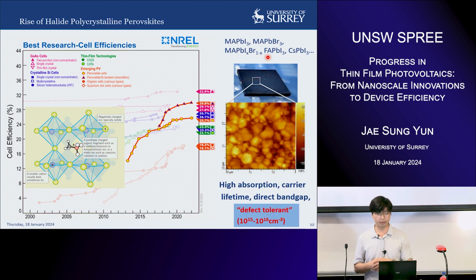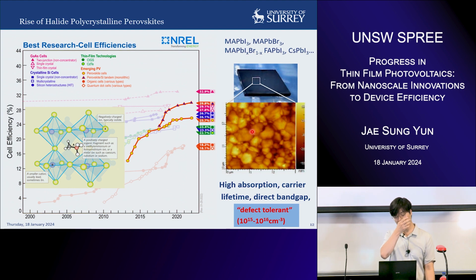A good thing about halide perovskite is that it is known to be defect tolerant. When I first saw this material, you could see that there are obviously a lot of grain boundaries. Grain size is around 500 nanometers, and nowadays the highest efficiency devices still have a lot of grain boundaries. People are reporting that this material is defect tolerant. The defect density is around 10^15, up to 10^16. If you compare it with silicon solar cells, it's very hard to understand how such a defective material can deliver such high performance. So it's good to study what these defects do in terms of performance.